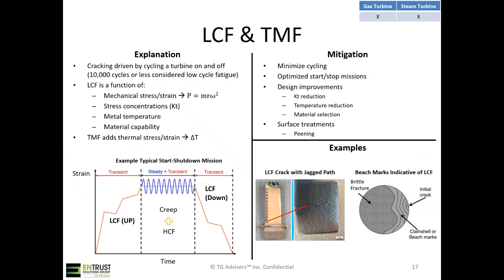It's also a function of metal temperature and material capability. Depending on what material you have inside of your unit or engine, it is going to be more prone to cracking. Thermal mechanical fatigue, the big thing there is that it's stress driven by delta T, so large temperature gradients. Typically in a gas turbine, for example, your stress is a combination of mechanical stress and thermal, whereas in a steam turbine it's a little bit more mechanical because you don't have as large thermal gradients as you would in a gas turbine.